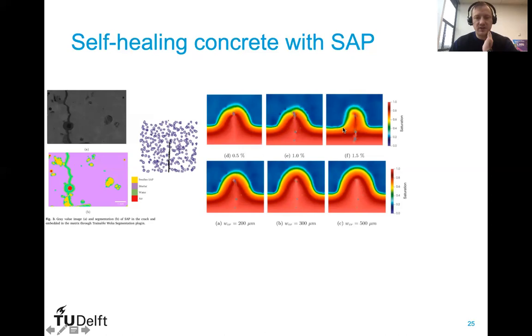So for different percentages of SAPs ranging from 0.5% to 1.5%, we see that our model is able to predict that less and less water saturation around the crack happens if we increase the SAP percentage, which is what we expect. Furthermore, we can also examine how crack width influences the sealing of this concrete with SAP. So we see that as we increase the crack width, we have more water penetration around the crack, even with the same amount of SAP. So there is a balance between how much SAP you need to put and how big cracks you can heal.